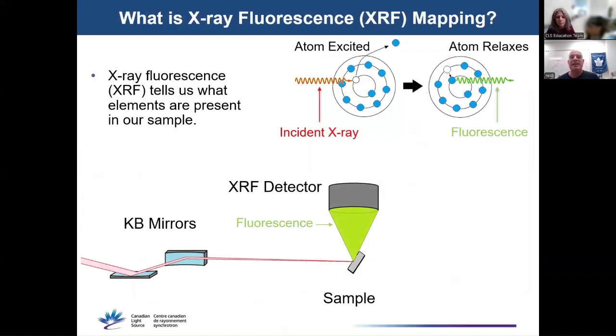One of the main strengths of the synchrotron is the high intensity, which allows us to collect data really quickly. So if you use a very small beam, you can move your sample horizontally and vertically in steps in the beam to obtain the elemental composition at every point. And you can use this to create really detailed 2D maps.